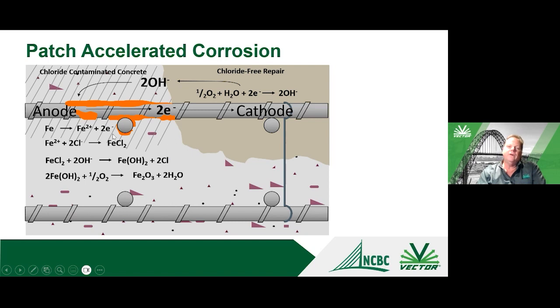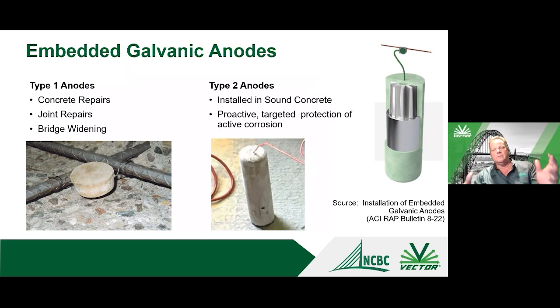Now you still have a high probability you have chloride contaminated concrete surrounding the repair. And now, instead of the corrosion being in the repair, it's going to want to shift to the area adjacent to the repair. And that's this halo effect or patch accelerated corrosion. And eventually you'll see new corrosion cell occur, just from the difference in the potential between the repair and the surrounding concrete.